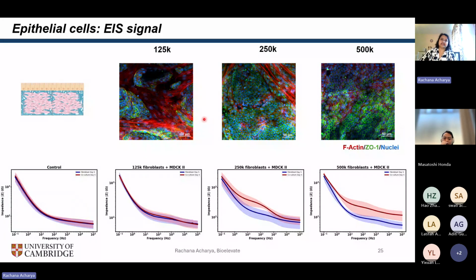So the moral of the story, so to speak, is that the formation of this kind of nice stromal layer of the fibroblast is really crucial for having good epithelial barrier integrity. And if I want to test the effect of different things which are going to disrupt my barrier or make it stronger, I need a very robust measurement for forming this barrier. And I need a very robust system where I know that it's suitable for these epithelial cells to form their barrier. What we can do with this device is measure both of these things independently. Using the transistor, we can measure growth of the fibroblast cells. And then if I have a good measurement, I know that my devices are ready for seeding my epithelial cells, and then I can monitor the epithelial barrier integrity with my impedance measurements.